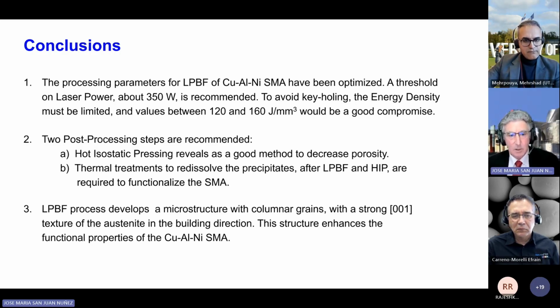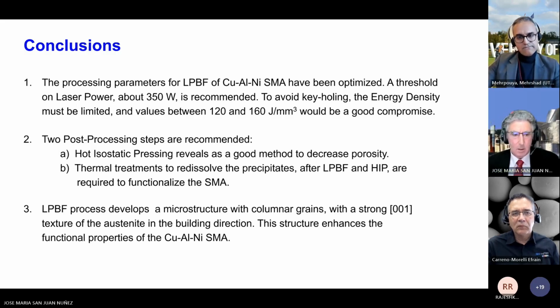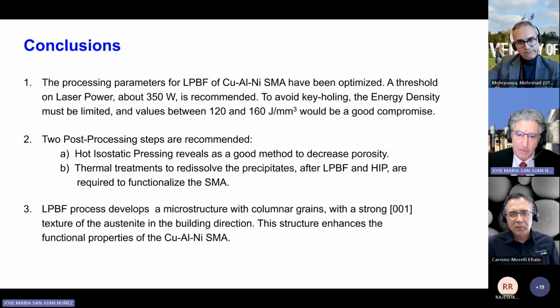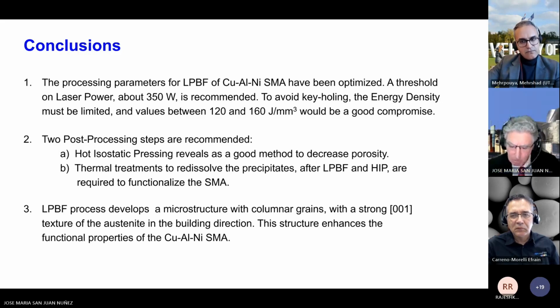And in the case of laser powder bed fusion, thermal treatments must be applied to redissolve the precipitates after laser powder fusion or after HIP, or both of them. These thermal treatments are required to redissolve the precipitates and functionalize the shape memory alloys. The laser powder bed fusion develops a microstructure of columnar grains with a strong 001 texture that is good for the thermomechanical properties. This structure enhances the functional properties of copper, aluminum, and nickel shape memory alloys.